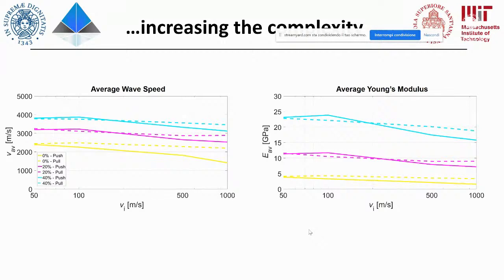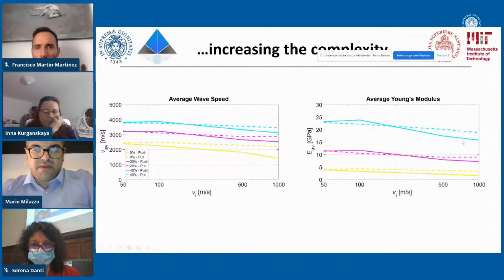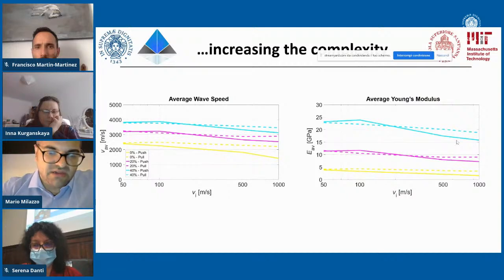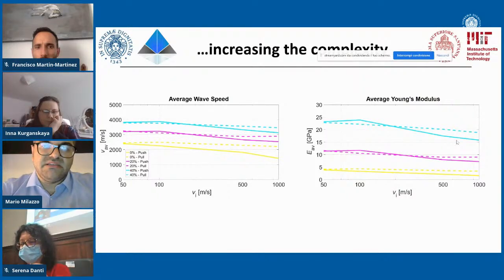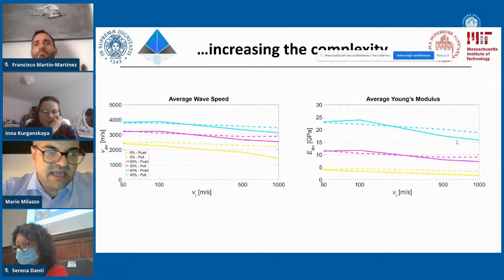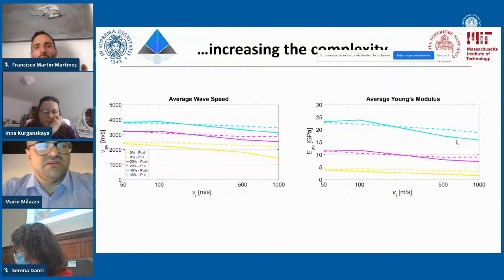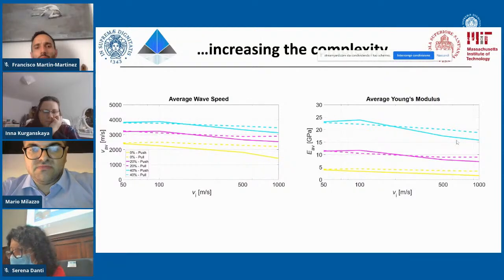So what we can see is this. Increasing the input velocity, we have a decrease of the wave speed and a decrease of the Young's modulus. This is an apparent contrast with other simulations that can be done on single peptides, in which if we are stressing with impulsive loads, we are increasing the Young's modulus. But in this case, we are not considering only a single peptide, but we are considering a complex topology in which multiple peptides are connected through hydrogen bonds, and those hydrogen bonds will play a significant role in transmitting energy and dissipating energy also.